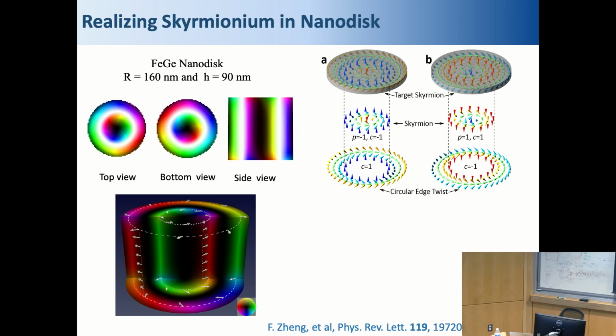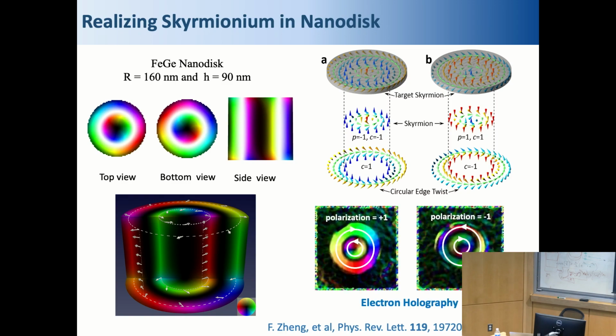Since there is no external magnetic field, two configurations that are time reversal to each other share the same energy. This center spin down, then up, then down, or center spin up, then down, then up. They share exactly the same energy. So there are two types of skyrmionium, and these are also realized experimentally by this electron holographic measurement. But this skyrmionium is confined in the disk.